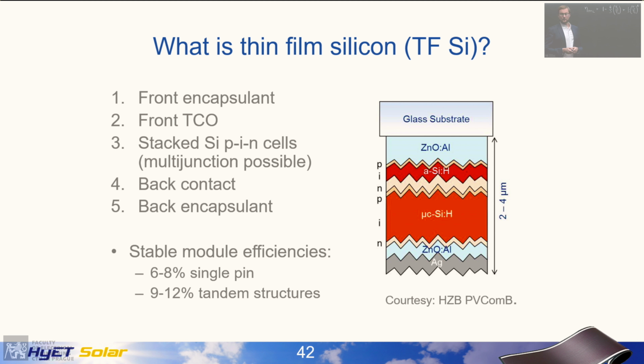Then we have different stacks of silicon. At the bare minimum you have PIN. So the I layer is the absorber. And then you have also a P layer and an N layer to serve as carrier selective layers for the holes and electrons, respectively. What you can also do is put multiple junctions of these materials on top of each other with different band gaps. For instance, this example here, where we have amorphous silicon first, and then microcrystalline or nanocrystalline silicon as a bottom cell. Then we have a back contact, and then some back encapsulant. So this is the basic structure that many groups worked on in Europe.